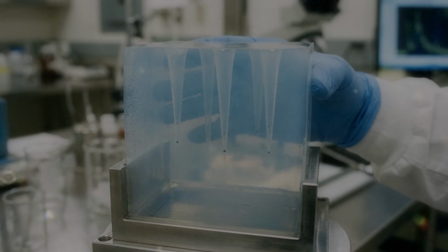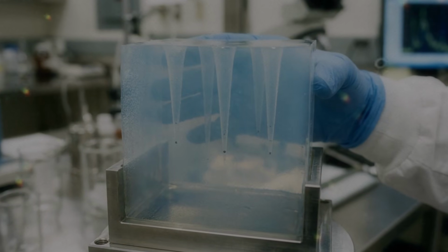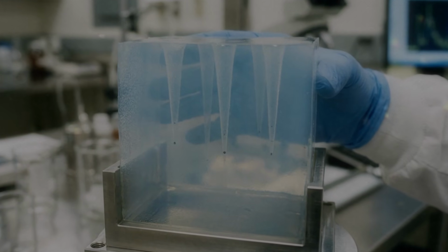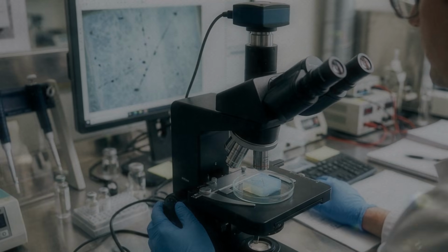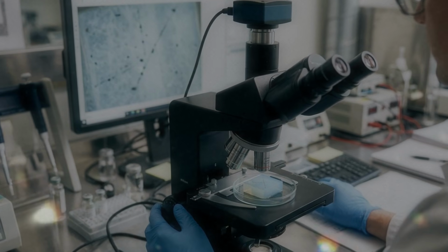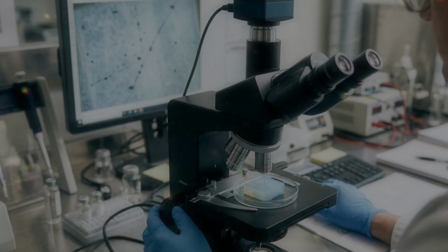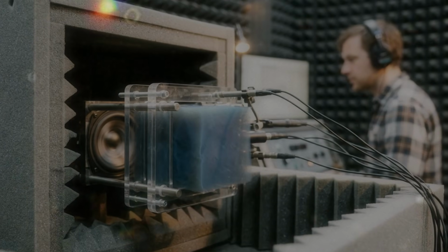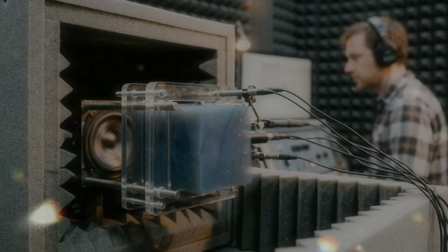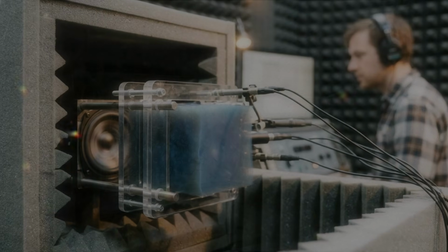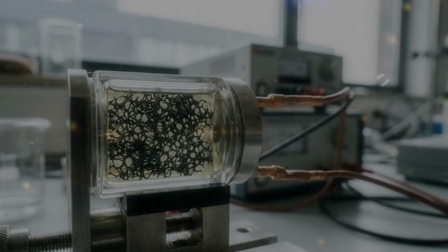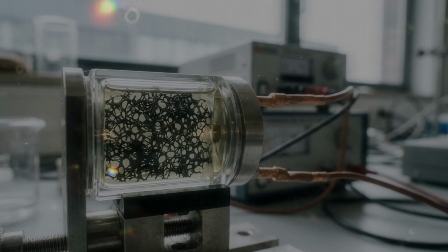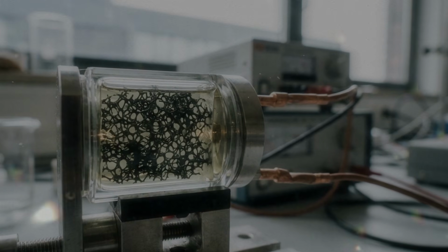The starting material is often graphene oxide rather than perfectly pure graphene. Graphene oxide consists of thin carbon-based sheets carrying oxygen-containing groups. Those groups make the sheets easier to disperse in water. Pure graphene tends to attract other graphene sheets and stack together. Once stacked, it begins behaving more like a dense form of graphite, and much of the useful surface area disappears.